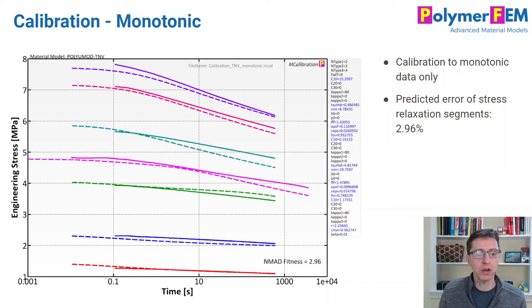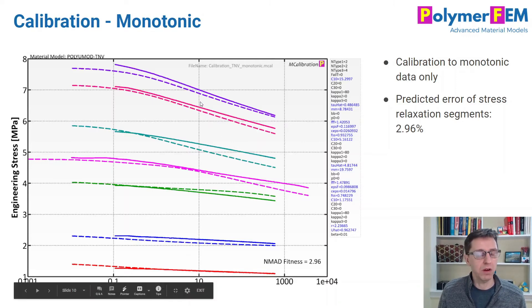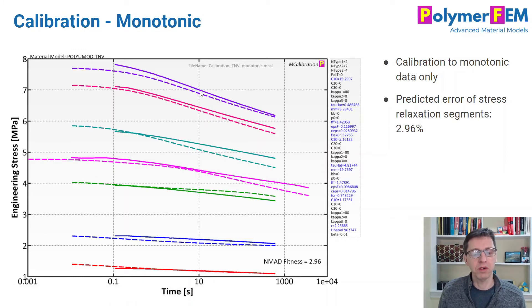There are a few other things you could look at if you're curious about the topic of linear viscoelasticity. If you look at this data here, is this a linear viscoelastic material model? If it was, the slope of these curves should be the same for each level of strain, and it's not. Therefore this is not a linear viscoelastic material model. If you normalize them by dividing the initial stress by the value, then by the strain that was applied, they should also get a constant curve for all conditions. I didn't plot that, but that's something you can look at if you're interested.